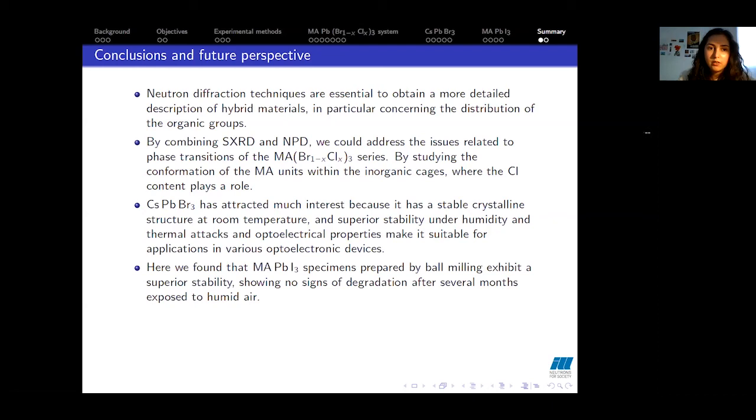Okay, and then Laura actually was correcting me. She has more experience with ball milling than me. And she's saying that even if you have hard balls, you can have some contamination. So one has to be careful. But zirconia, I don't know its atomic number. I'm not a chemist. I think it's sort of in the middle of the periodic table. So it would probably show up on X-ray. Actually, zirconium has an atomic number of 40 and lead has 82. So they are much different. So you get about a factor of 5 once you take the square.